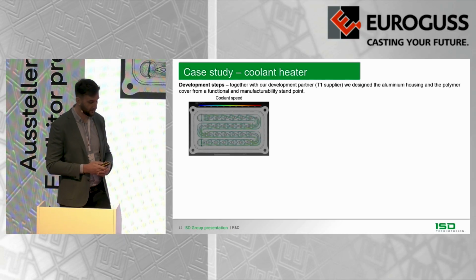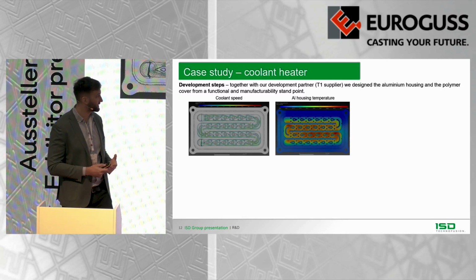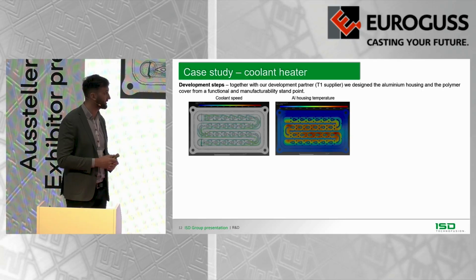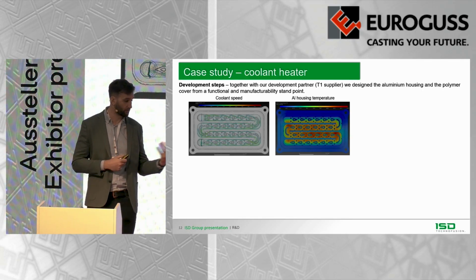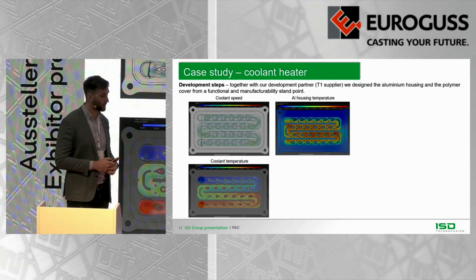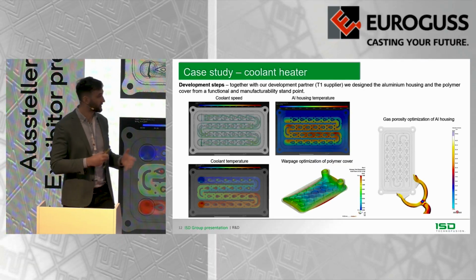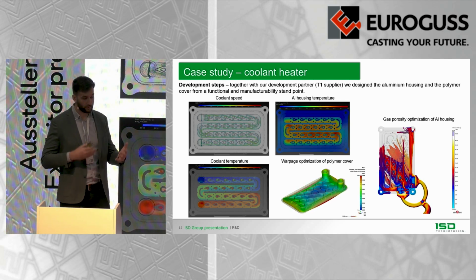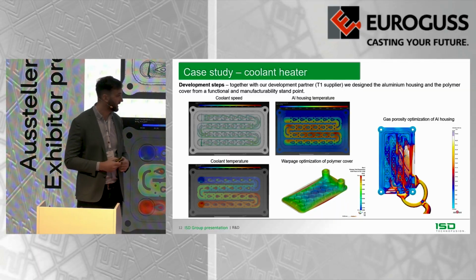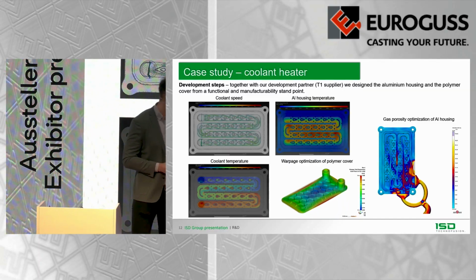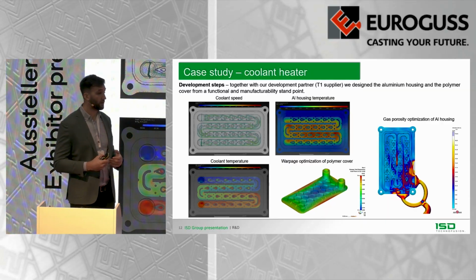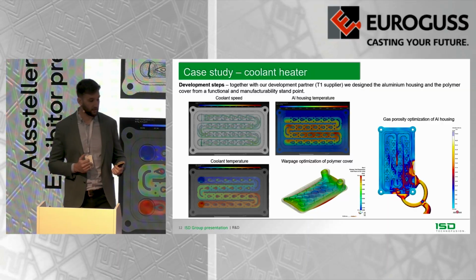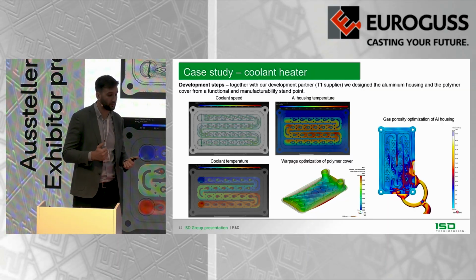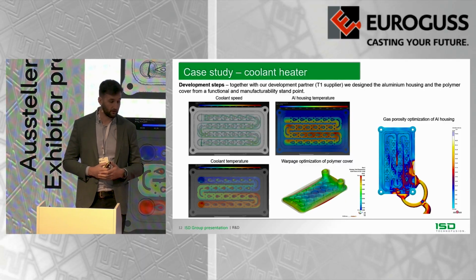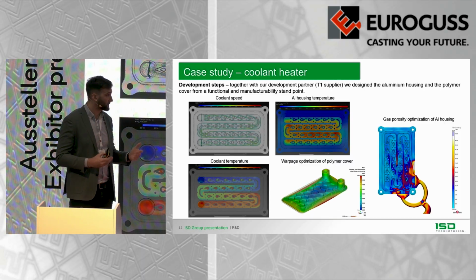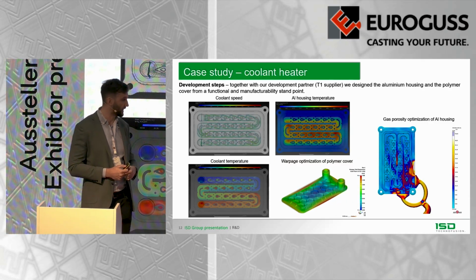So obviously there were some development steps so that we designed the right design of the fins. Our partner made several iterations to reach the best flow, the best heat removal from the aluminum to the medium. And we also did several simulations to make the part manufacturable, to have low gas porosities, so all the usual suspects from casting. On the other side, a lot of effort was also put on the design of the polymer part, because it needs to be flat, and on the polymer selection itself, because even though many of the casters are not so well informed about polymers, polymers in many cases, even mechanically, are better or can be better than cast materials. And that's why we proceeded in this direction of substituting metal covers with polymer covers.